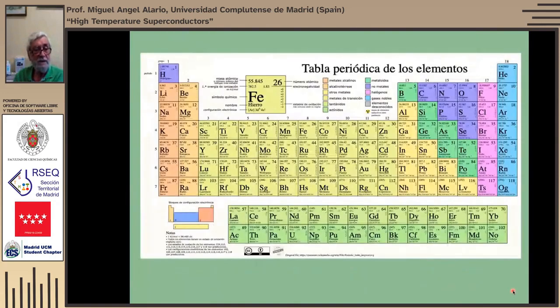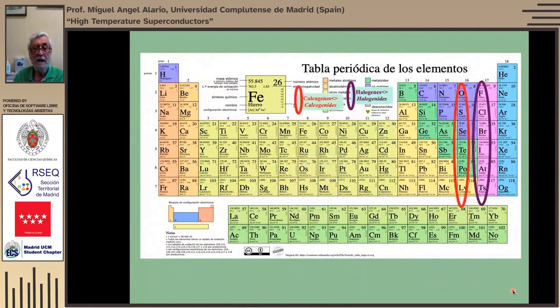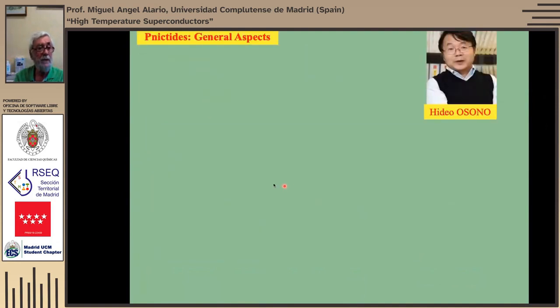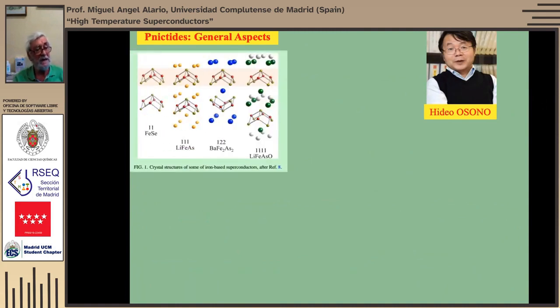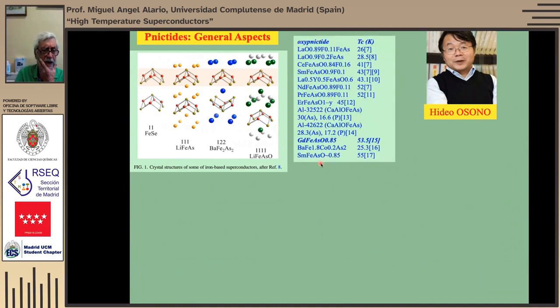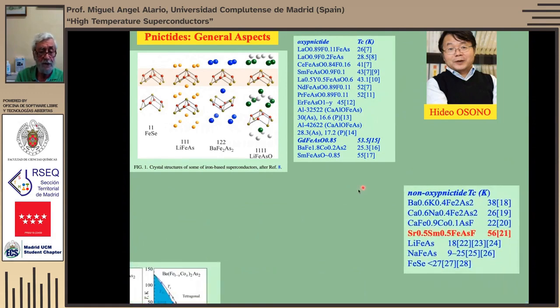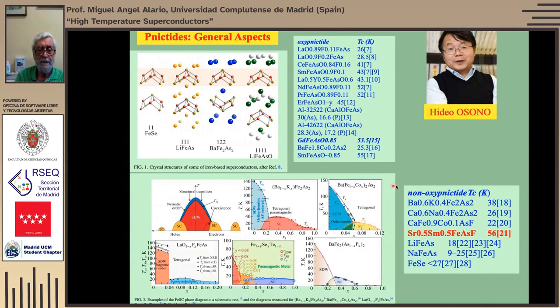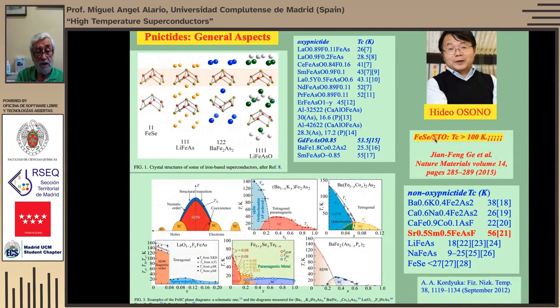Well, pnictides, not very interesting, because now they are superseded by others. These are halides, these are chalcogenides, these are pnictides. And then there is a big family of pnictides discovered by a good friend, Hideo Hosono. These are similar materials to YBCO in the cuprates, in the sense that they are also layer structures. But the critical temperatures are much lower, and they have arsenic and things which are not easy to use in industry. But also the critical temperatures are rather low. There is an exception. Well, these are the phase diagrams, which are very, very nice. And then this is iron selenide, which has apparently a very high Tc, but this is a complicated material for some reasons.